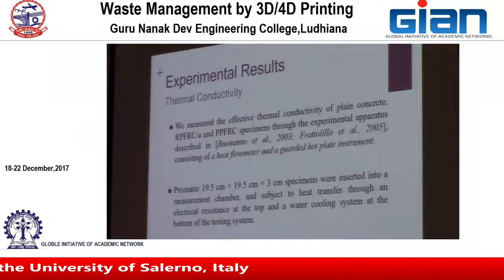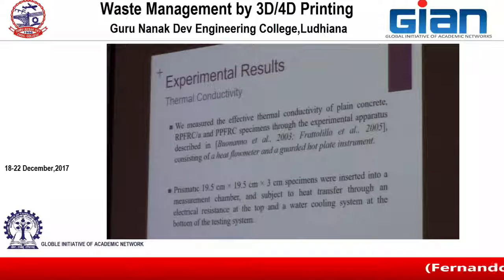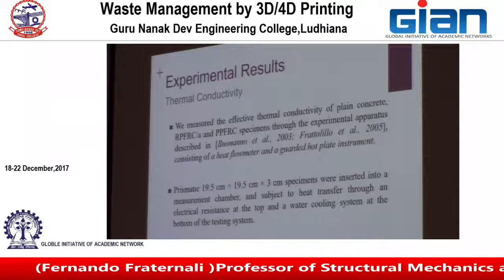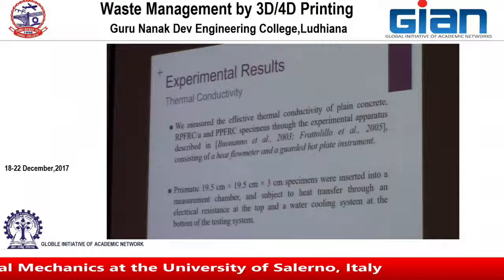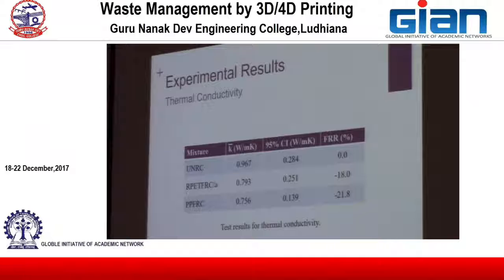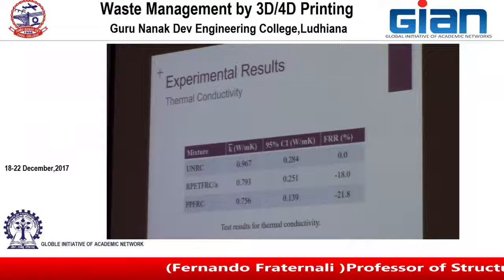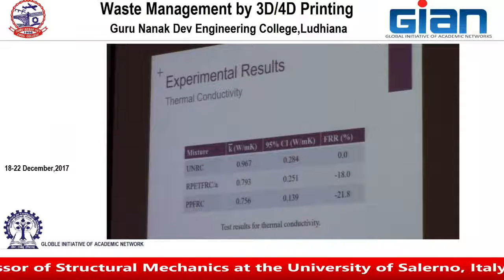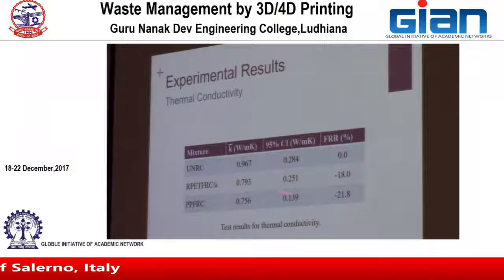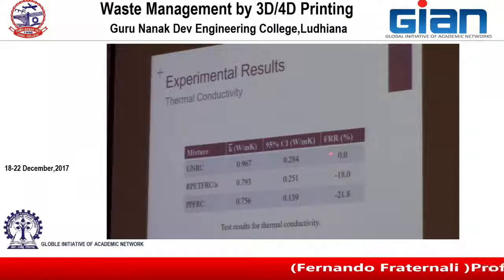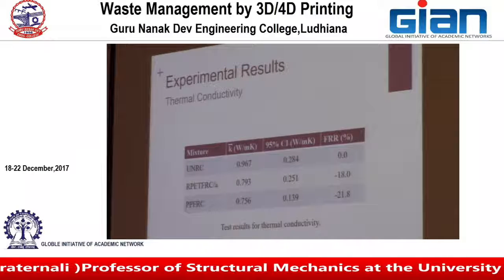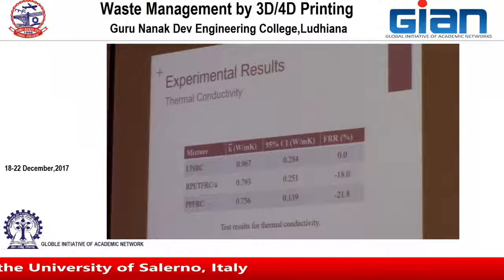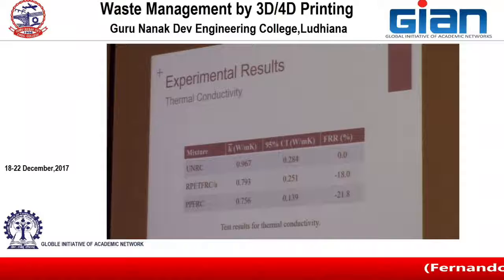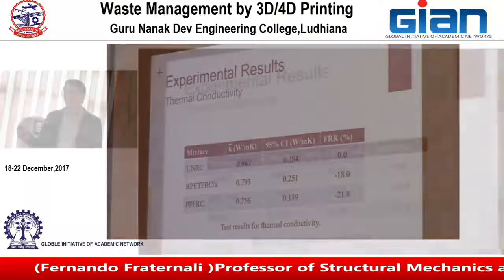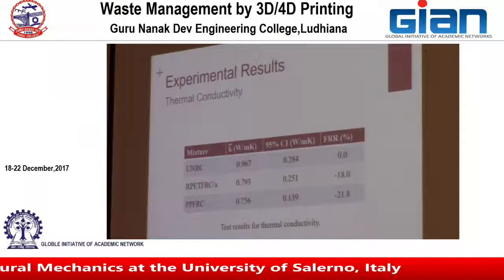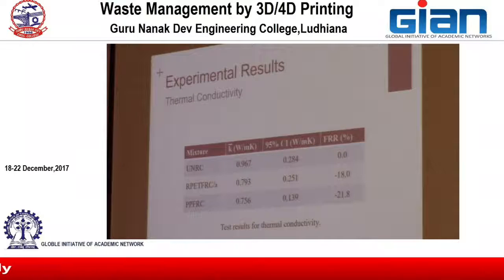For the thermal tests, the prismatic specimens of 20 by 20 by 3 centimeters were inserted into a measurement chamber and subject to heat transfer through a standard system for measuring the thermal conductivity. What we observed is that the thermal conductivity was markedly reduced by mixing concrete with plastic fibers. This FRR, which will be shown in different tables, is the fiber reinforcement ratio. So it's the percentage variation of a given property in presence of fibers as compared to the same property in the unreinforced concrete, so in absence of fibers.